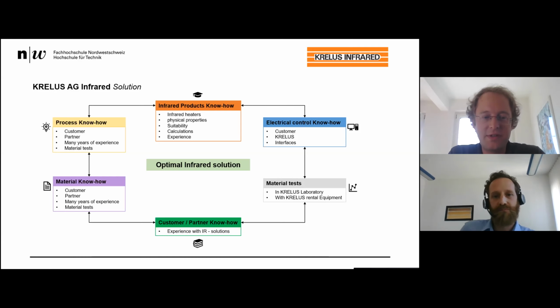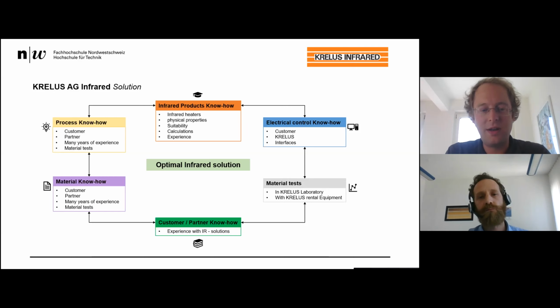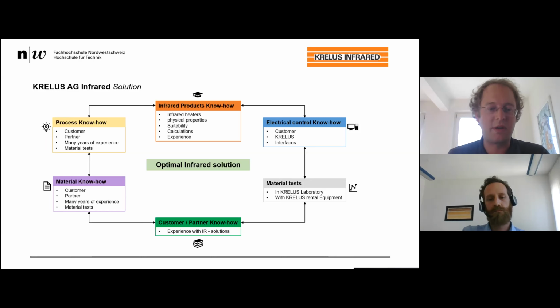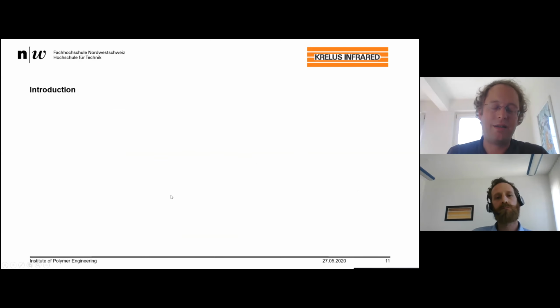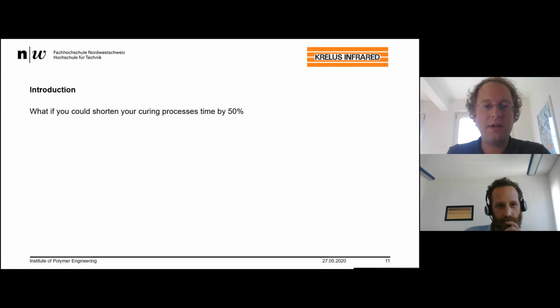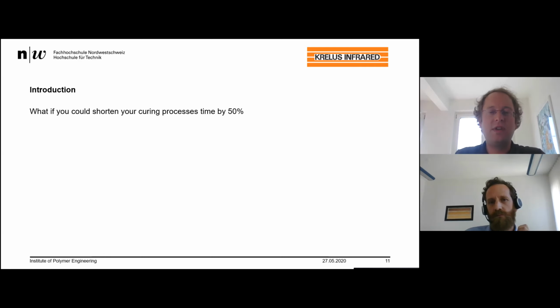So what Silvio has introduced is that we have a heater which has really nice properties, can heat up really fast, and in addition, we are able to customize the heaters and building heat fields with separate elements which we can apply for advanced control. And this was the starting point. So normally, Krelus systems are mostly used in the composite industry by heating up thermoplastic materials or organosheets and so on. And our idea and approach was, what is happening if we apply this technology not to heat up a thermoplastic material? What will happen if we use the technology to control the curing process?